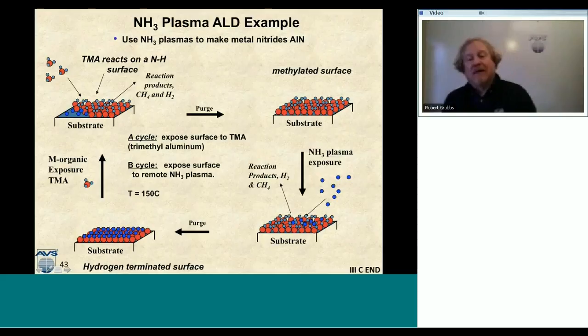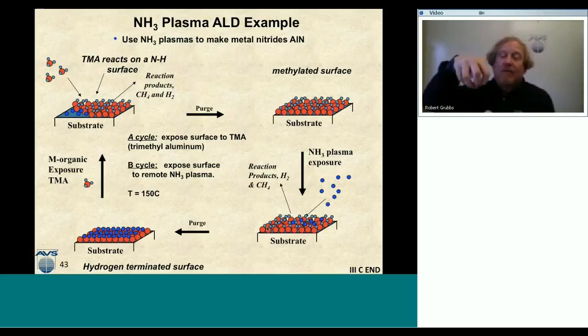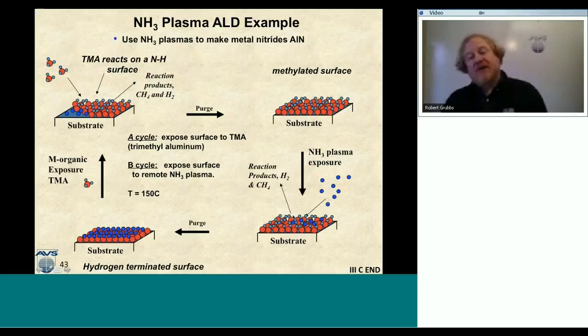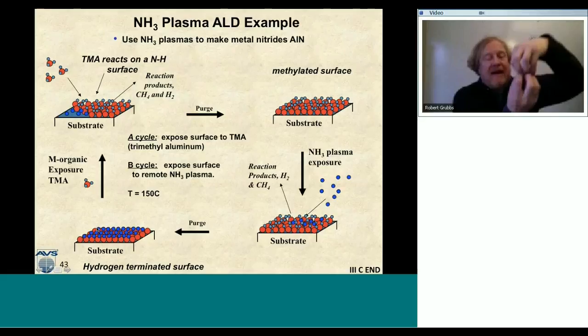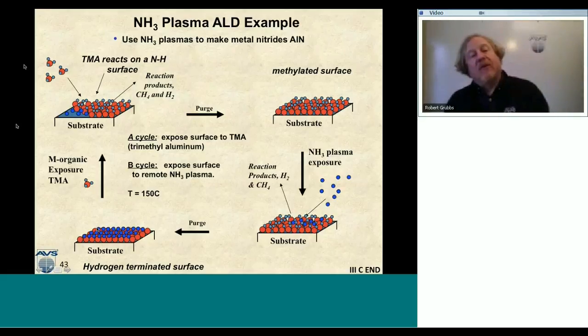I'll take ammonia plasma and expose that. That ammonia plasma will react away those methylated groups on the aluminum and make a nitrogen aluminum bond. And then once that's done, I'll produce products of probably hydrogen and methane. Once that's reached surface saturation, I've got this aluminum nitride surface, and this surface is terminated by NH bonds that are going to then re-react with the trimethyl aluminum as I come down to my A step. So these are two plasma examples, and that's the plasma ALD section.